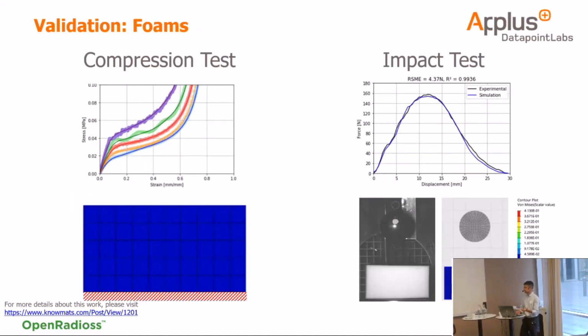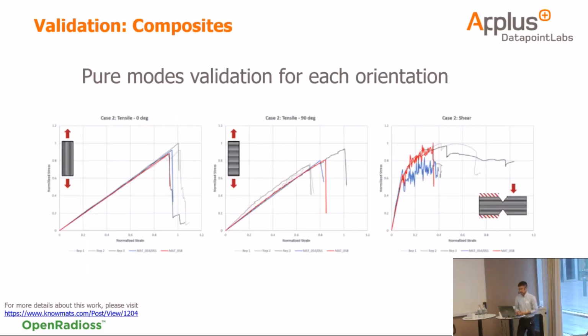You can see for the simple compression tests and the strain rate, it matched the experimental data pretty well, and for the impact test, it matched perfectly, both the loading phase and the unloading phase. And finally, in composites, for this project, we validated just the pure modes, two tensiles at different orientations, and then the shear, which was a little bit noisy in terms of simulation, but it worked pretty well also.